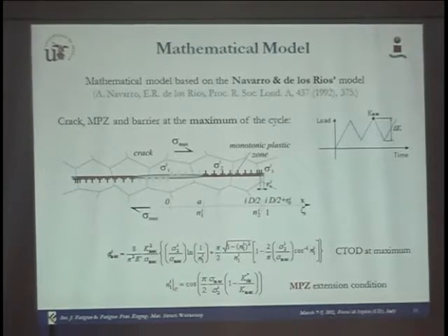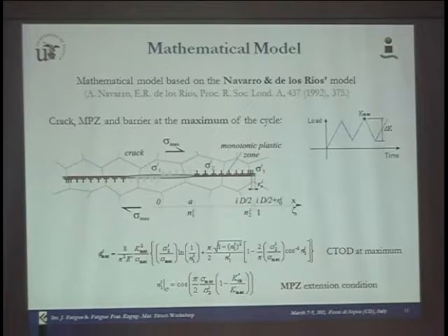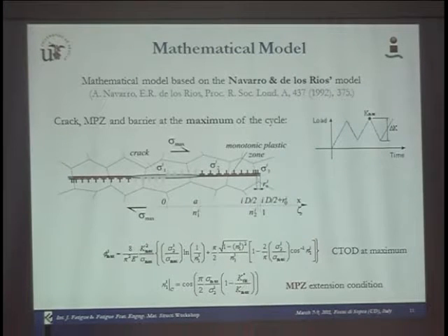To model this, we use the model of Navarro and de los Rios, which is a one-dimensional model based on distributed dislocation technique to model the crack, to model the plastic zone, and to model the barrier zone. It's a simple model, but it's effective, at least for our purpose.